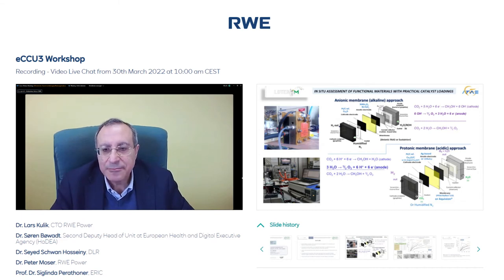Slide number three, please. Okay, now regarding the reaction process, we can clearly see that in the anion exchange membrane environment, of course, we can get advantage of a larger carbon dioxide solubility at the interface between the electrode and the electrolyte. And of course, we need the presence of hydroxyl ions at the anode for the oxygen evolution reaction. This is really important that for this reason, we recirculate hydroxyl ions. We recirculate a KOH solution, diluted KOH solution at the anode.